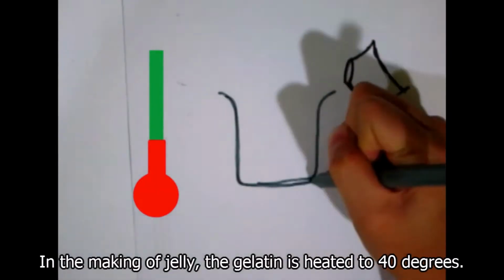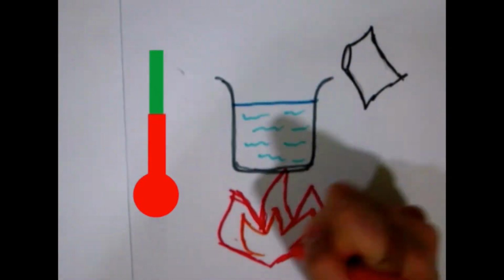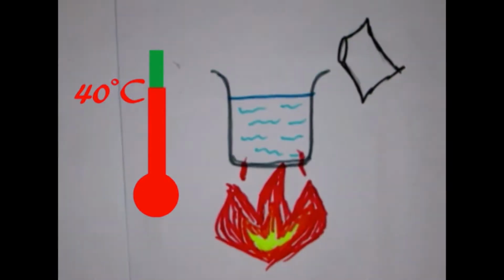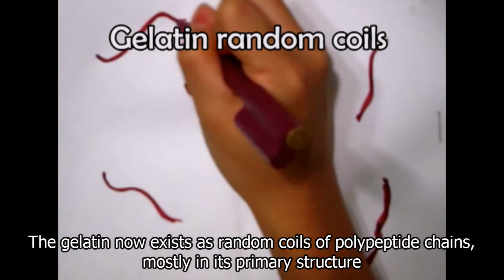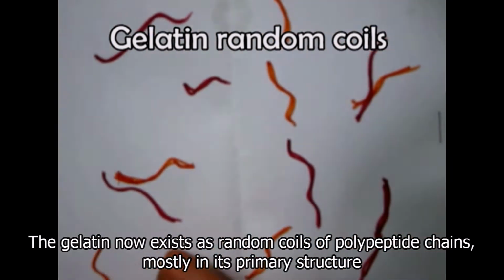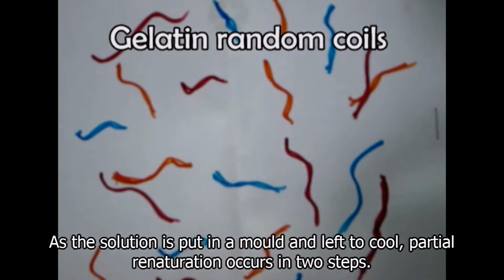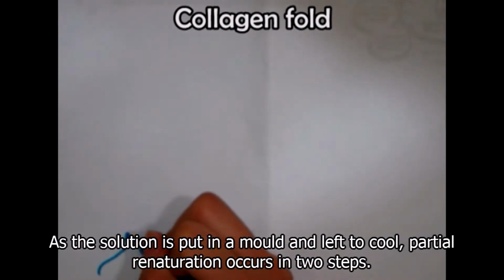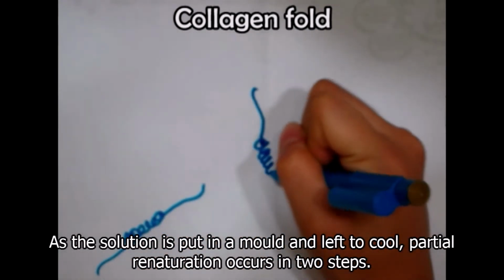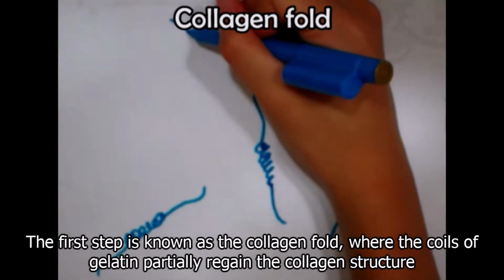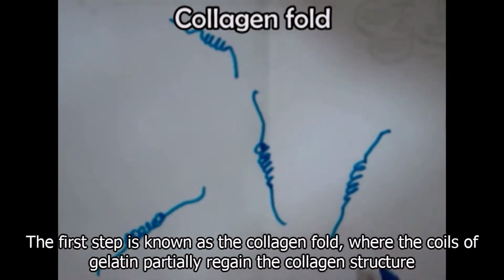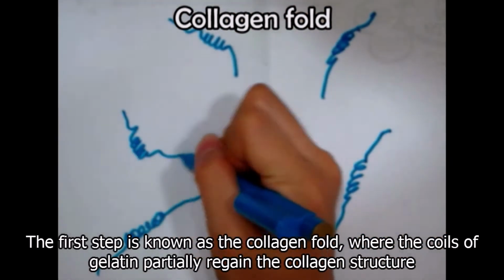In the making of jelly, the gelatin is heated to 40 degrees. The gelatin now exists as random coils of polypeptide chains, mostly in its primary structure. As the solution is put into a mold and left to cool, partial renaturation occurs in 2 steps. The first step is known as the collagen fold, where the coils of gelatin partially regain the collagen structure.